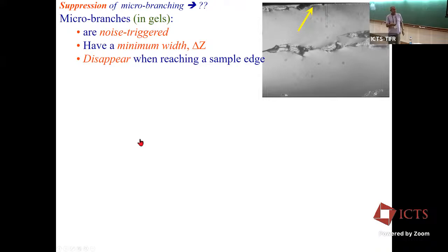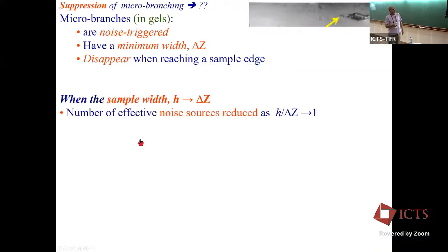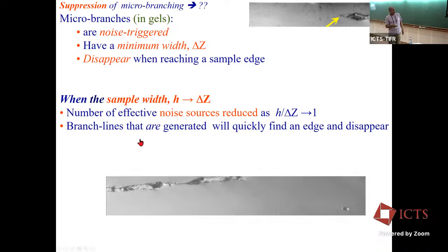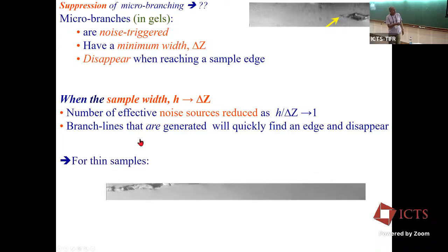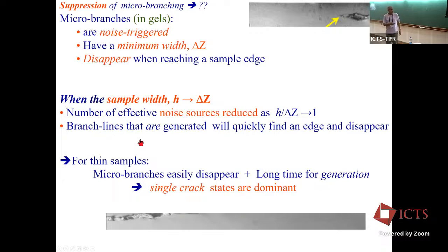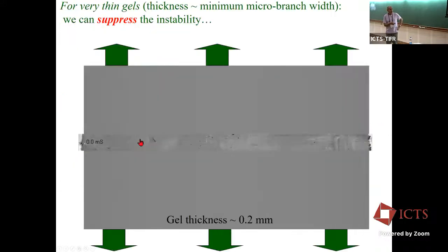So as a result, if we make these samples thinner and thinner, we can get to a point where there are very few of these micro branches. They disappear, and we can have long sections where we have simple cracks once again. And when we do that, for example, we can test the equation of motion beyond the onset of this instability. And we'll do that in a second. Right now, these single crack states, as I'll show you, can accelerate to nearly the Rayleigh wave speed.